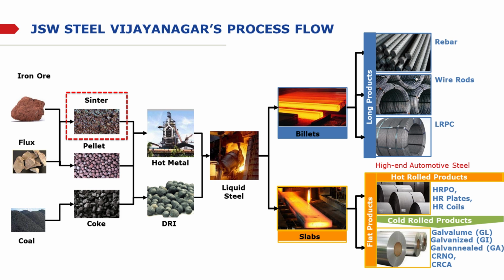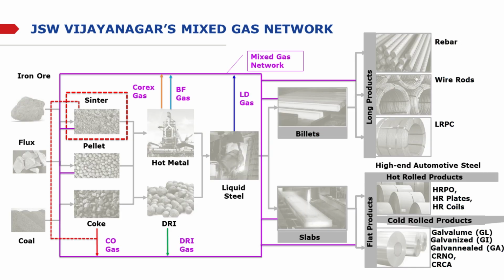The liquid steel is cast in continuous casting machines to produce slabs and billets. The slabs are rolled in hot strip mill and cold rolling mills to produce flat products. The billets are rolled in wire rod mill and bar rod mills to produce long products. The byproduct gas generated from coke oven, Corex, blast furnace, LD, and DRI are mixed, and is called mixed gas. The mixed gas is used for various heating applications in the entire integrated steel plant.